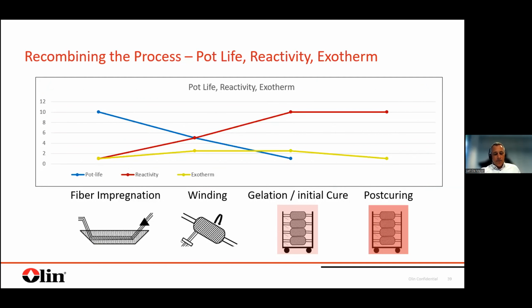If we look at the other parameters, at pot life, reactivity, and exotherm, I combined all of these in one graph because actually they are kind of dependent on each other. Pot life requires low reactivity in the liquid phase. Exotherm requires low reactivity in the entire process. So it looks overall a bit more complicated. And I would say overall, the key determining parameter for type 4 pressure vessels is definitely to manage the exotherm over the entire process. The critical point is really to keep thermal damage away from the liner material.